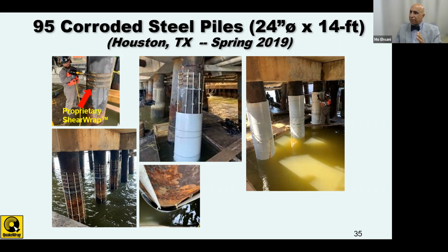But in strengthening these, there is something to keep in mind. As you realize, we are creating a ring of reinforced concrete around that pile. So if the original host pile is made out of timber or concrete, there is good bond transfer between this new ring of concrete and the host structure. But if the original structure is steel, you don't get a lot of good bond transfer. And as a result, we have developed this product called shear wrap.